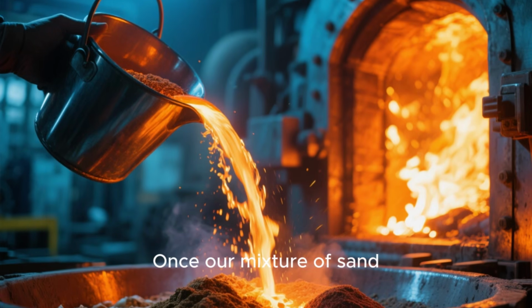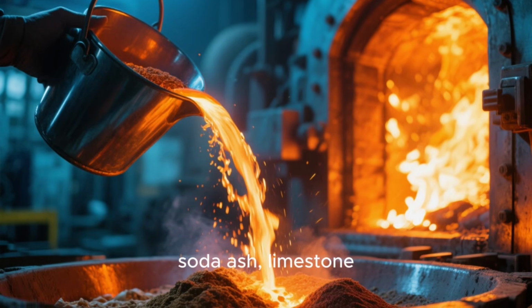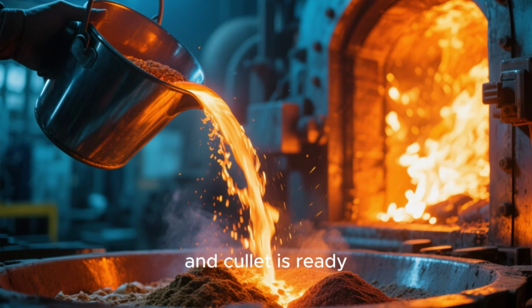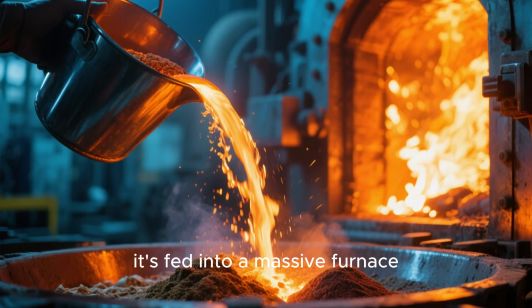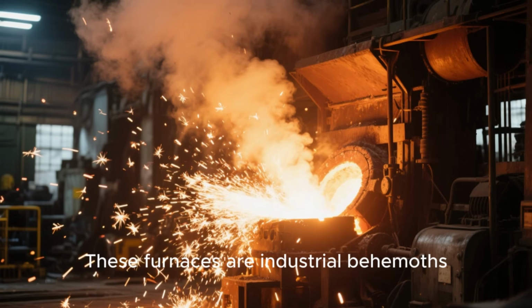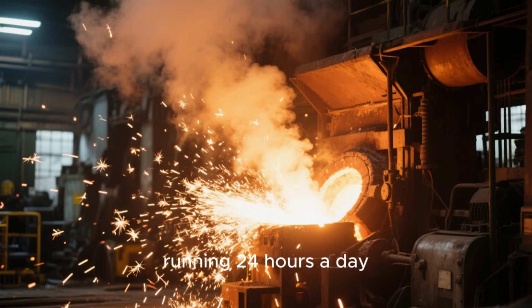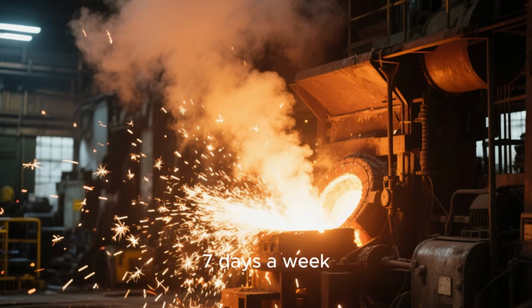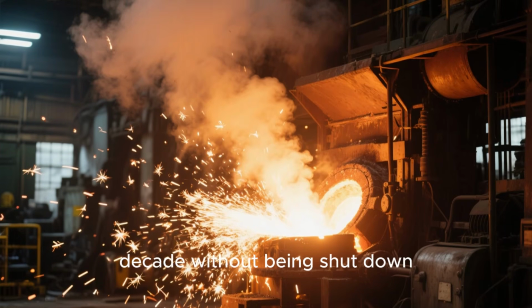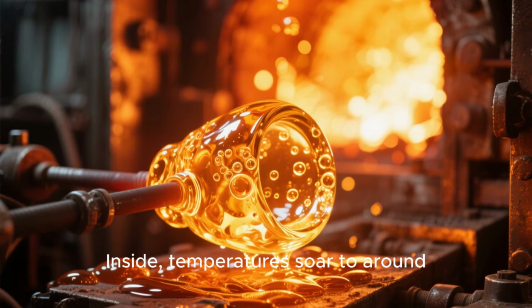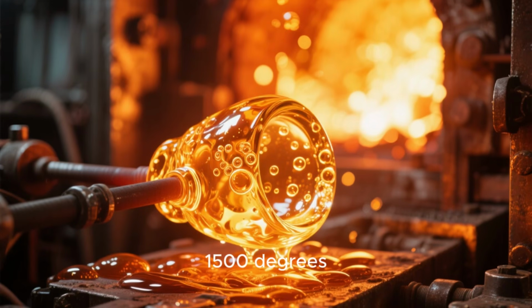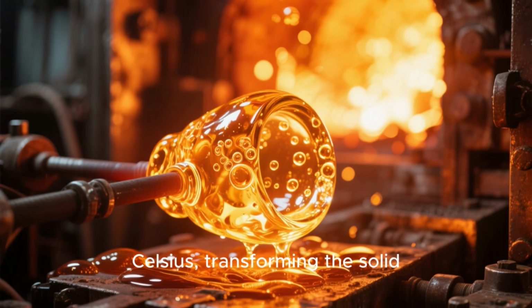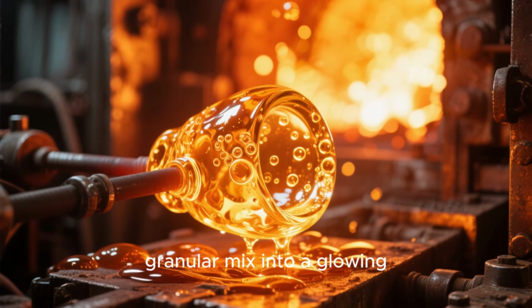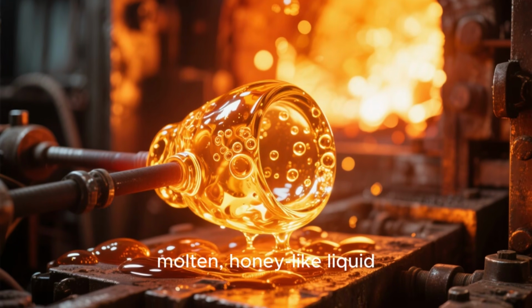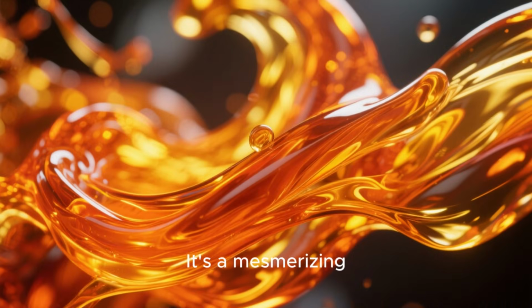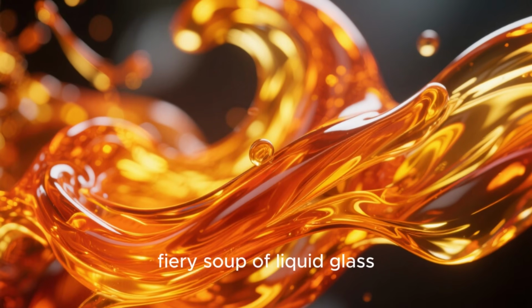Once our mixture of sand, soda ash, limestone, and cullet is ready, it's fed into a massive furnace. These furnaces are industrial behemoths, running 24 hours a day, 7 days a week, sometimes for more than a decade without being shut down. Inside, temperatures soar to around 1500 degrees Celsius, transforming the solid granular mix into a glowing, molten, honey-like liquid. It's a mesmerizing, fiery soup of liquid glass.